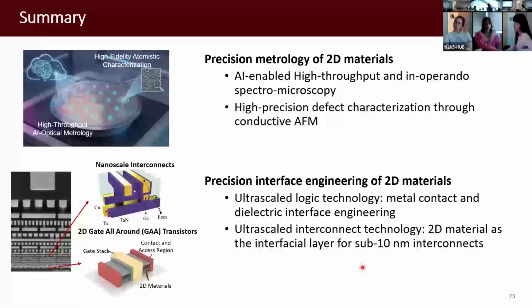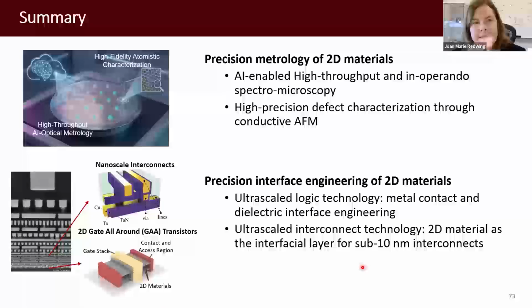But if we have a good definition of the system, and we take that averaging effect into consideration, we generate a data set to capture those effects, and then we train a neural network, it may be possible we can get more information. Instead of having the average N and K, we may be able to give you other information, like a percentage, layer by layer, or something. Yeah, we can, but we haven't.